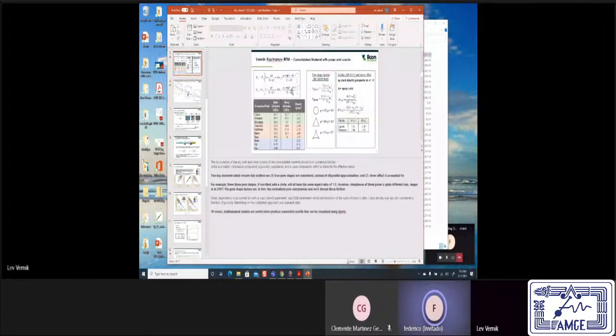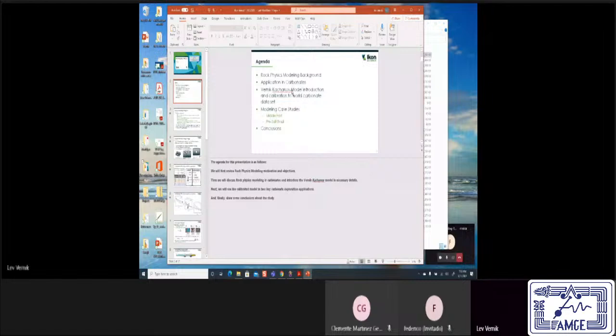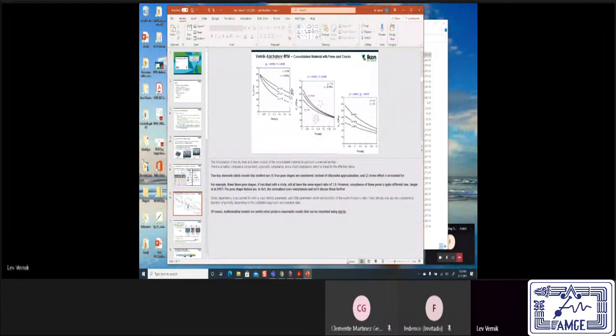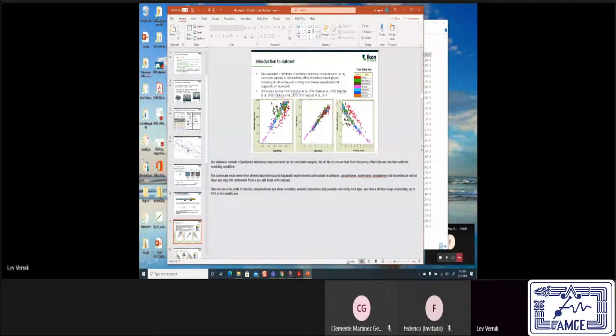So we just compiled a data set measured by some other people. And this data set seems to be pretty comprehensive. It covers a significant range of velocities and porosities in rock microstructure, in mineral composition, and porosity. And we applied our model to this data set pretty successfully, calibrating the model. And so we believe that this is the way to go if you want to learn something about the rock and apply forward modeling to compute logs from rock physics. We prefer that, at least in Ikon Science, and I know other people use it too.